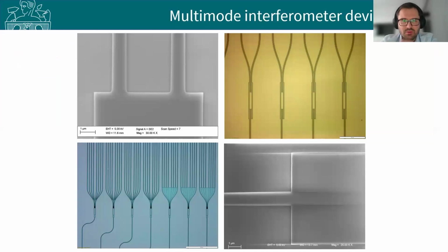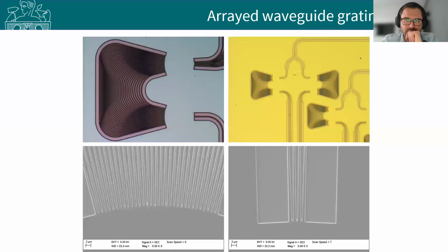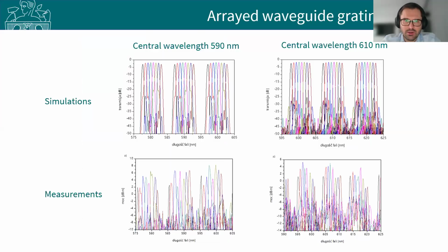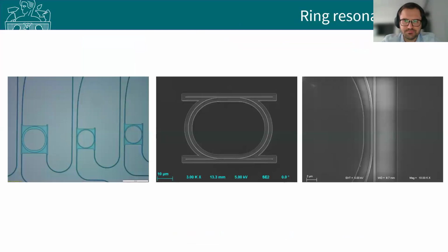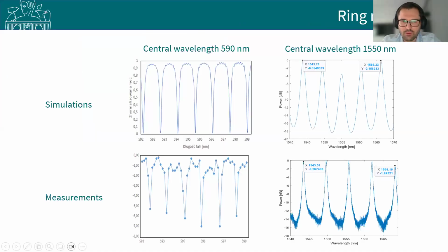Here you can see examples of multi-mode interferometers, arrayed waveguide gratings, which are especially difficult because of the small dimensions of the gratings. Comparison of simulation and measurements of these elements. Ring resonators, this one with an opening for the microfluidic interface, and also the gap between the bus and the ring here is below 100 nanometers. Comparison between simulation and measurements.